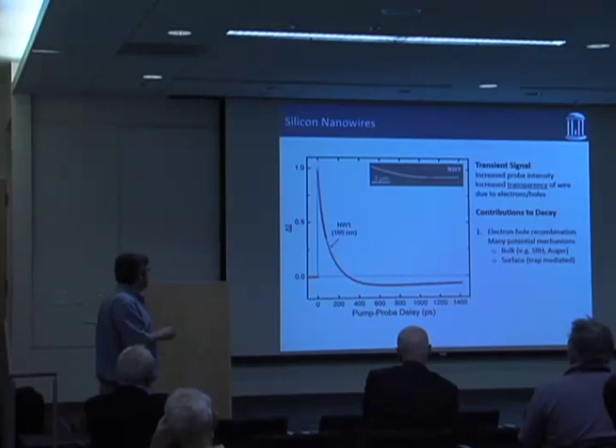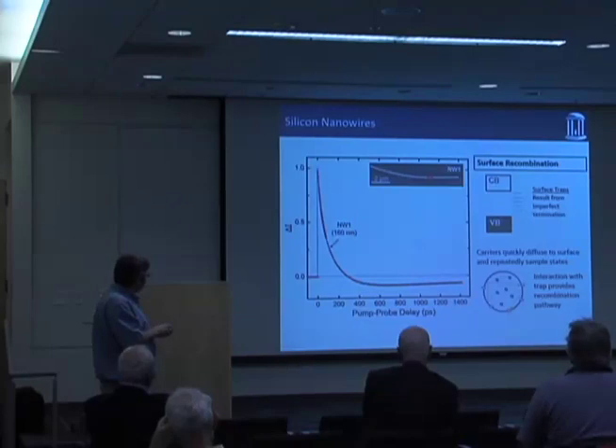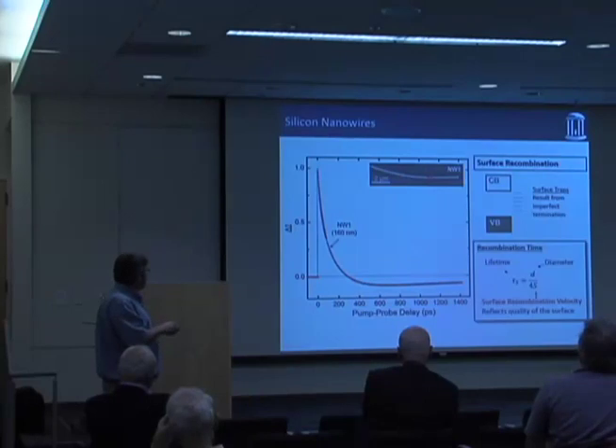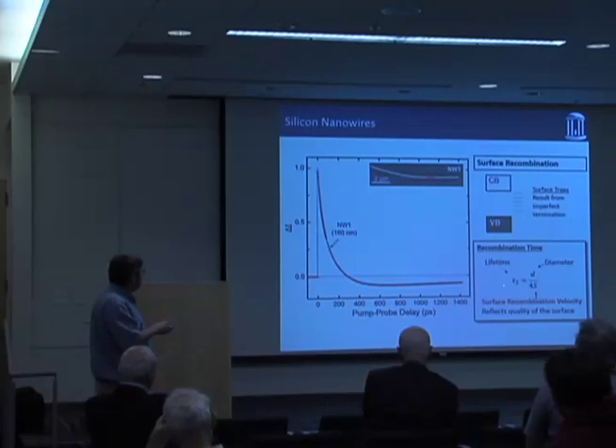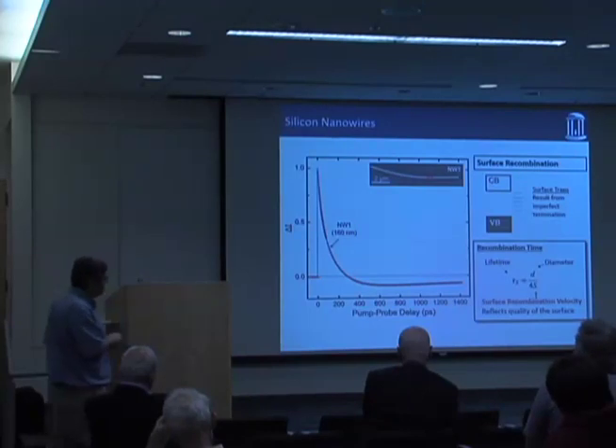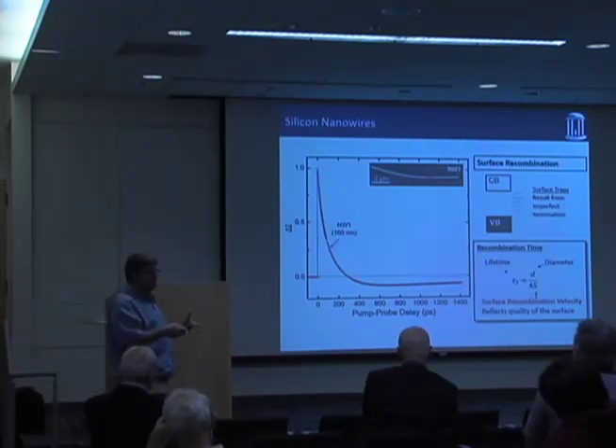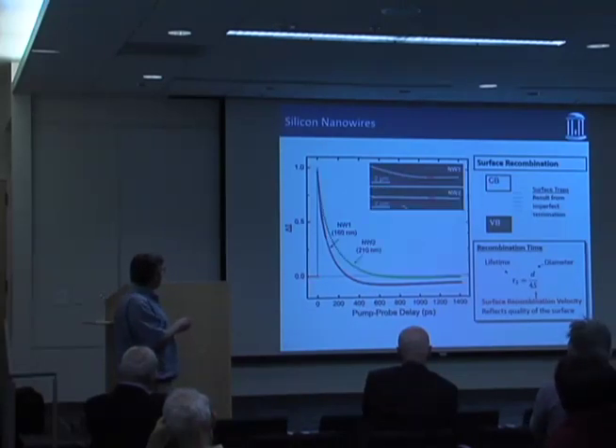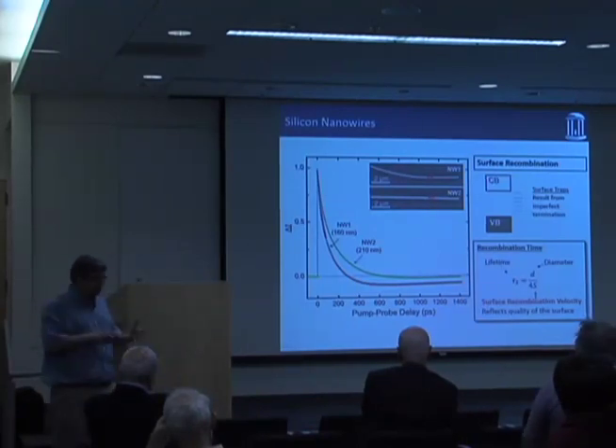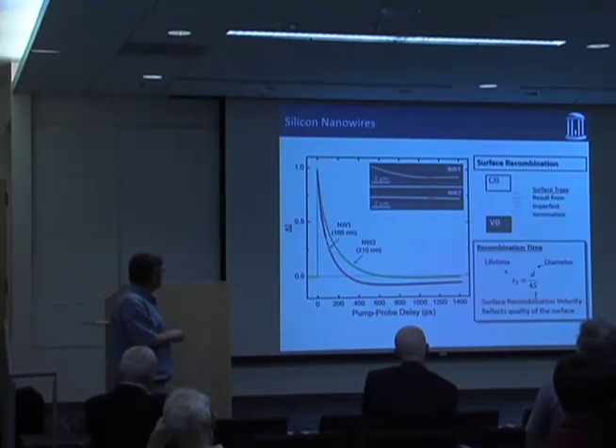And in nanostructures, that tends to be the dominant mechanism, but we could test that because as those carriers recombine at the surface, that lifetime should depend on the diameter of the nanowire. So if it is a surface-mediated event, the lifetime should depend on the diameter, and it's inversely proportional to this thing called the surface recombination velocity, which is a metric of the quality of the surface. But anyway, we could pick a different wire. So here's another wire. It's larger diameter, and sure enough, it slows down, consistent with the electron-hole recombination being dominated by the surfaces.